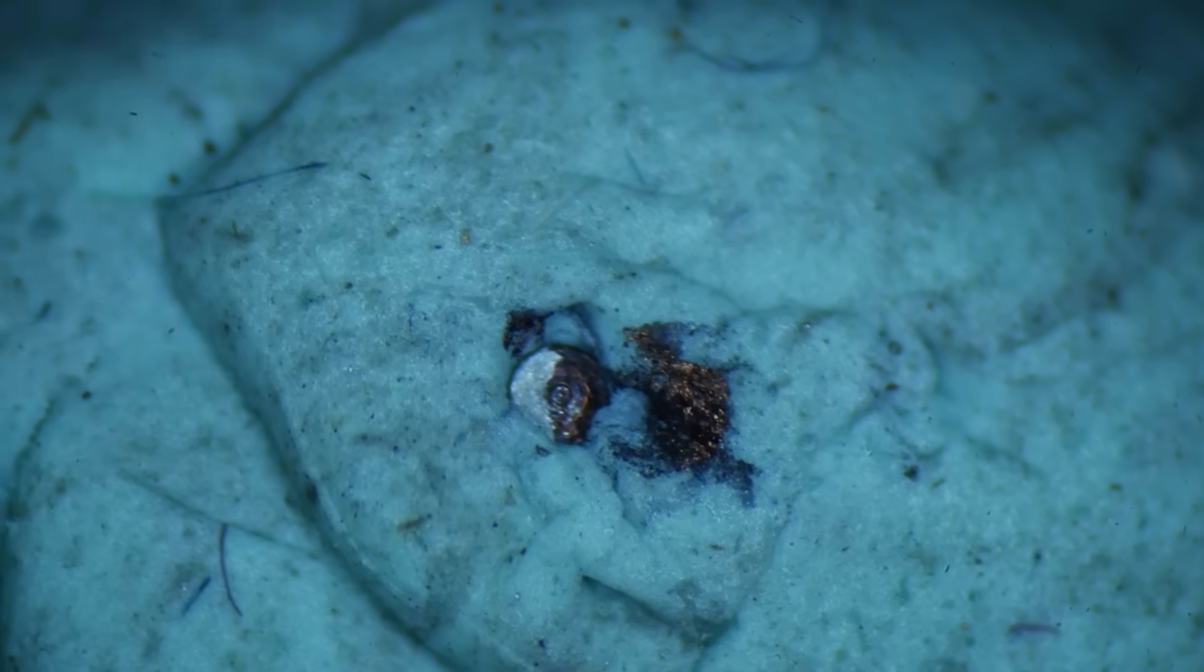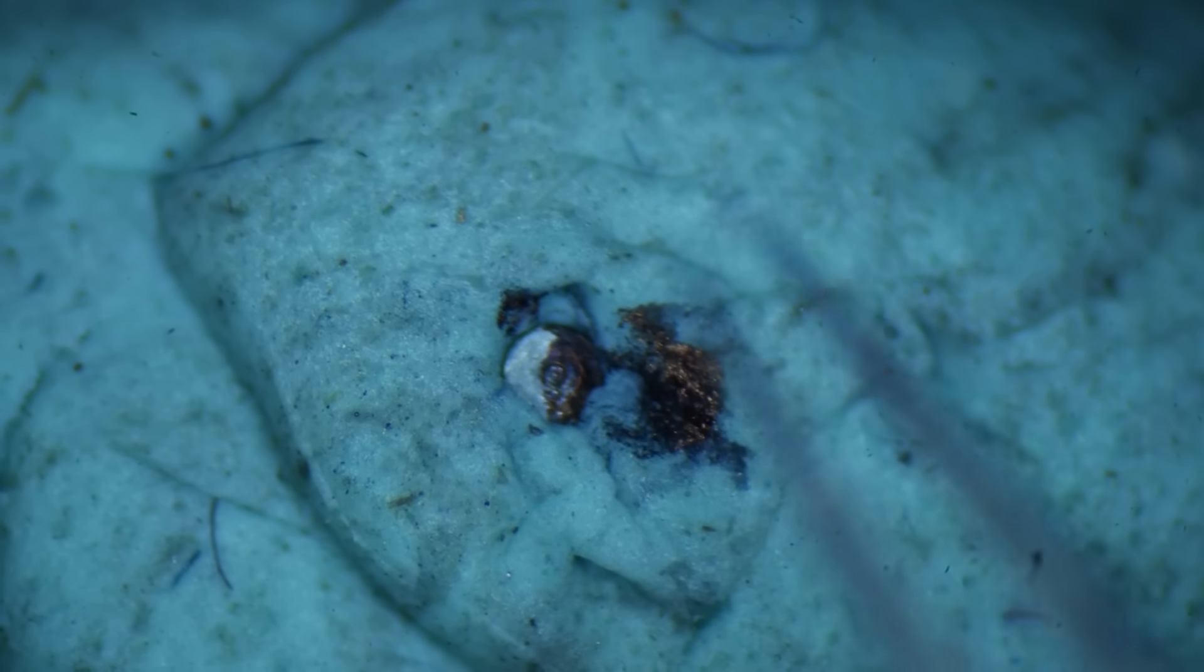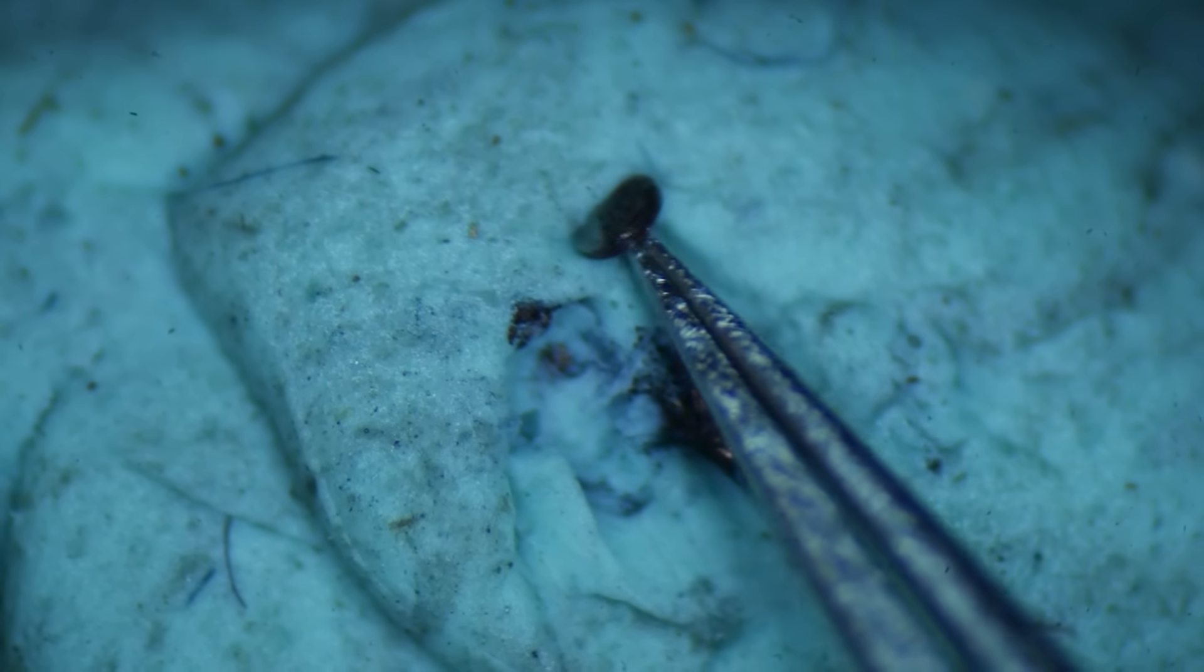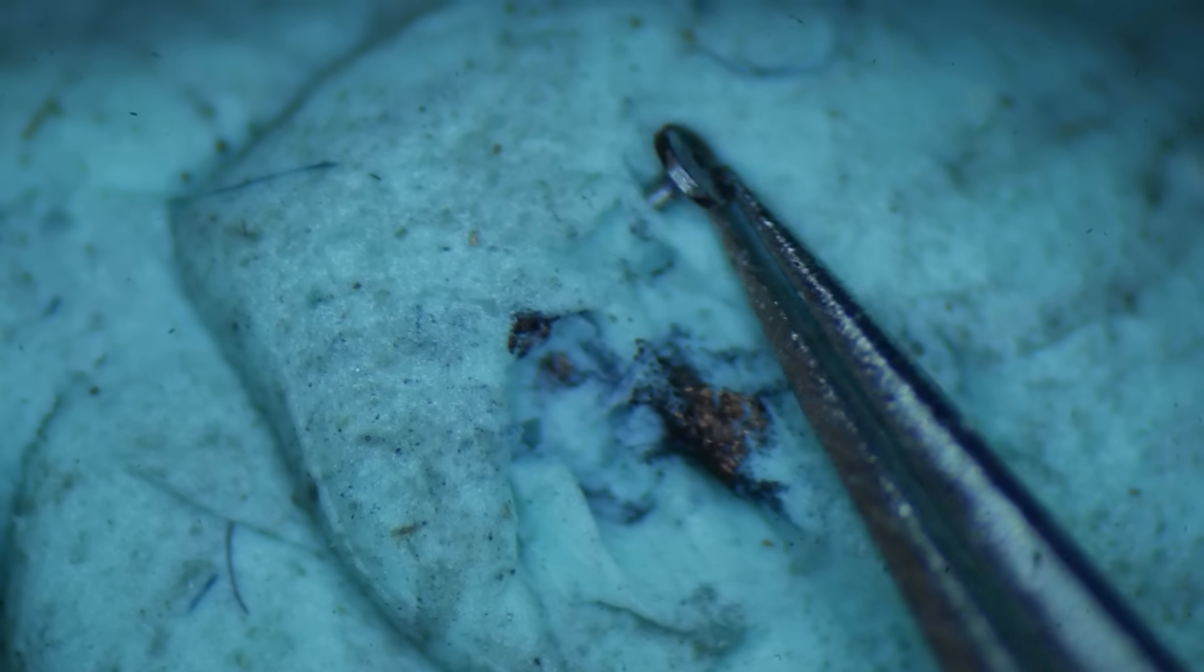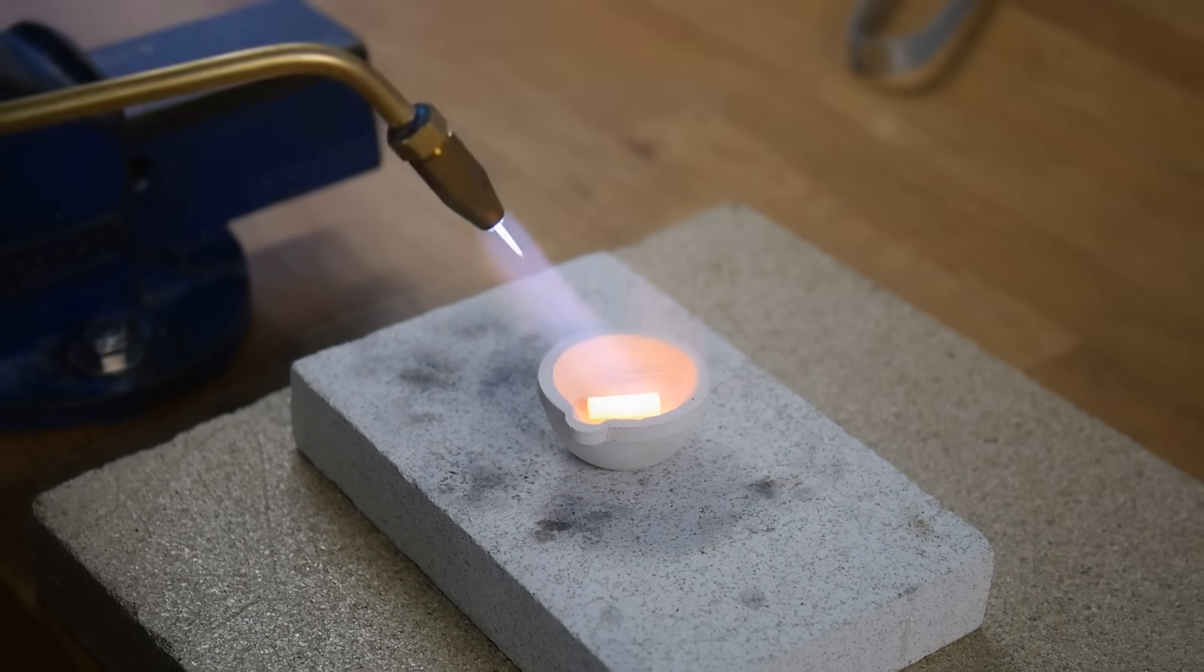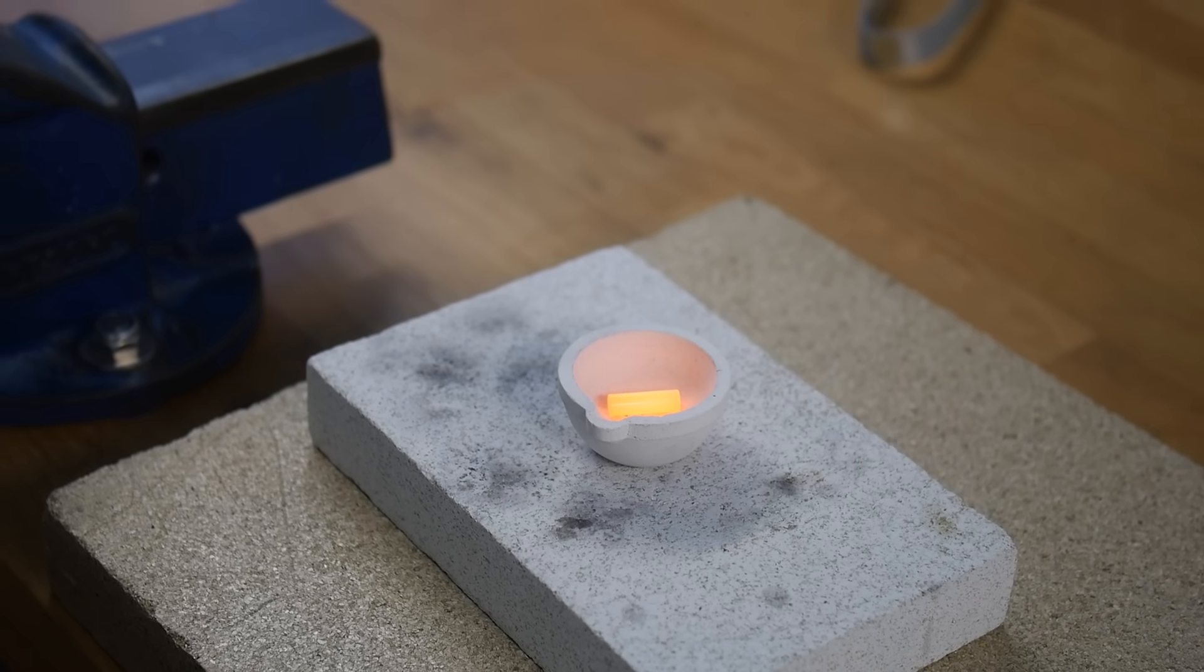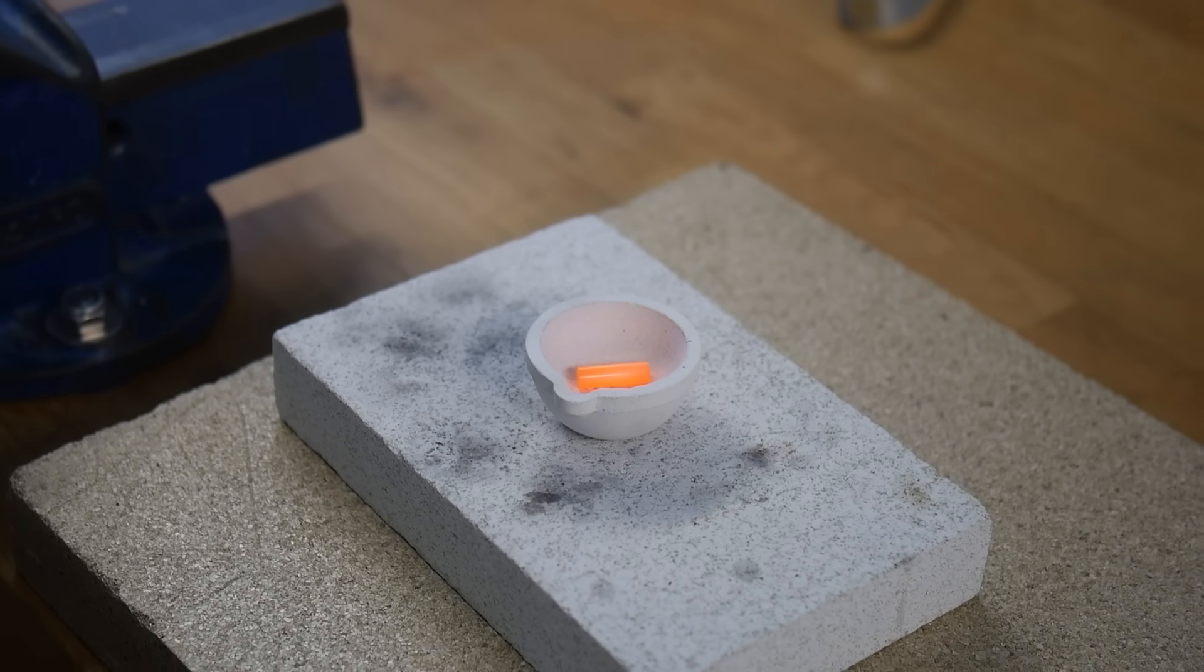I did some experiments on the rotor after the test run and realized that the rotor had lost its magnetism. In a way though, this was actually good news because this implied that the electromagnets were working and their magnetic field was overwriting the field I applied with the neodymium magnets earlier. My brother Charlie, who's an expert on magnets, suggested I use a material called alnico. I could only source this pre-magnetized, so I bought a piece and heated it up beyond what's called Curie temperature, and then I let it cool down slowly to demagnetize it.